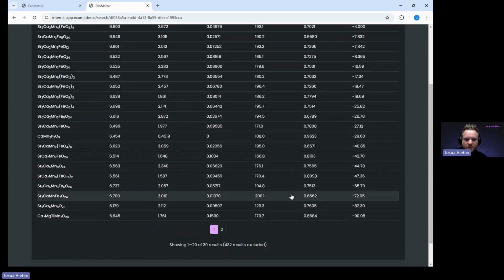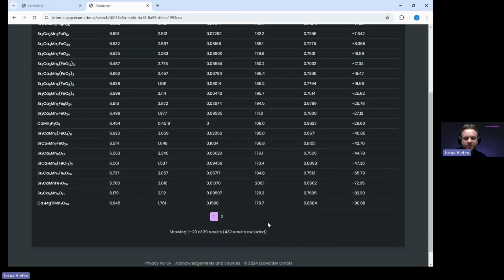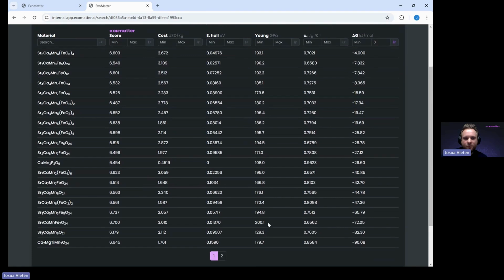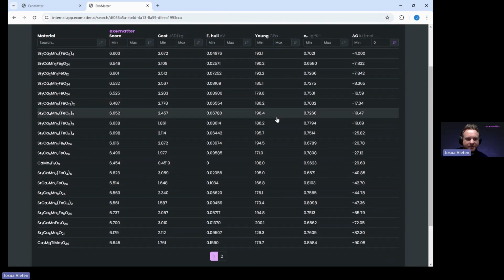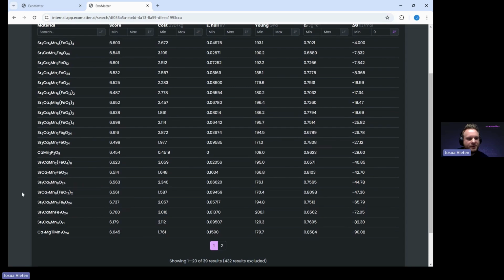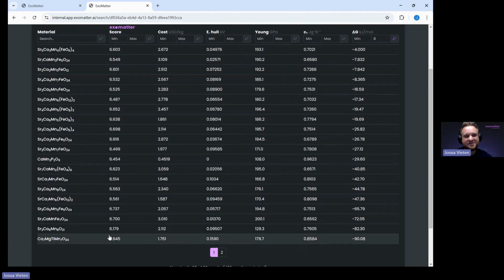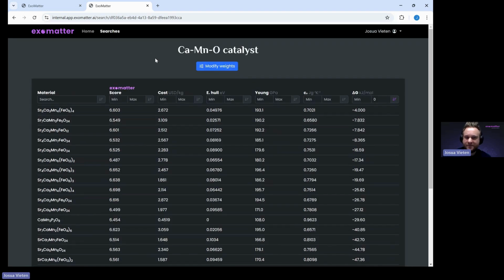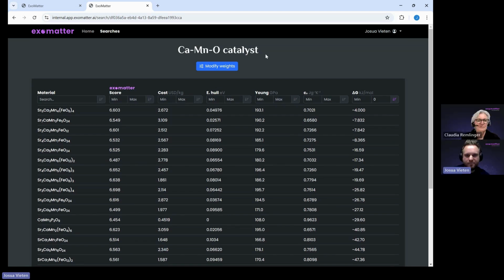Yeah, so you can see now we have filtered 39 results out of those 471 materials that were in the list where the reaction can occur. And you can see a lot of mixed strontium, calcium, manganese, iron oxides, but also some more exotic variants like this calcium, magnesium, titanium, manganese oxide. Very complex material indeed, but that's the strength of this platform, that we can identify very targeted, very complex materials very quickly. So with that, I will end my demo here and give the floor back to Claudia.